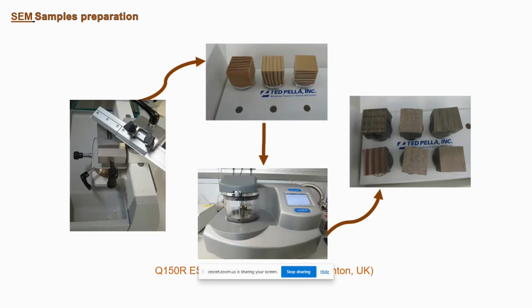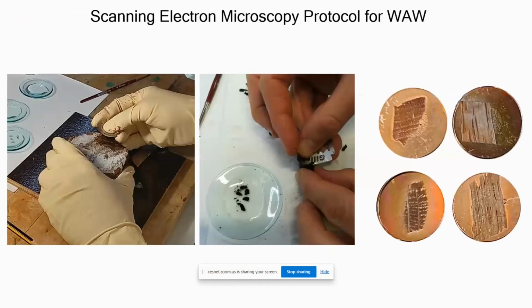But with the waterlogged archaeological wood, we have wet wood, and this cannot be inserted in this way in the SEM chamber, because the SEM chamber must be under vacuum, and also it must be cut in a way that we get a nice surface. So we decided to freeze the sample and to cut a thin slice with a razor blade by hand. And you see here these thin slices that are around 20 microns.